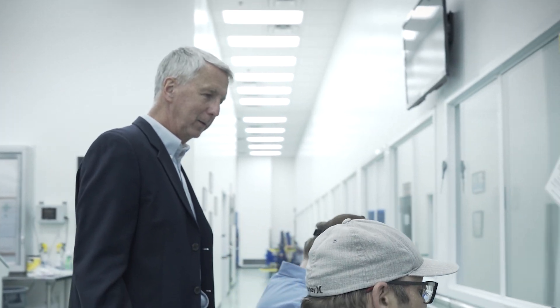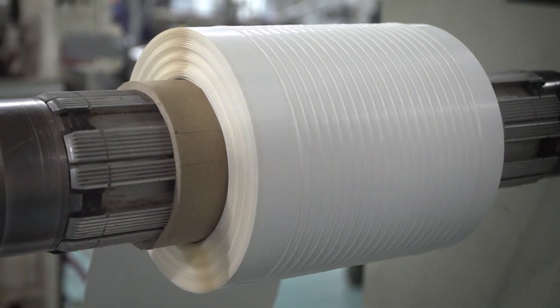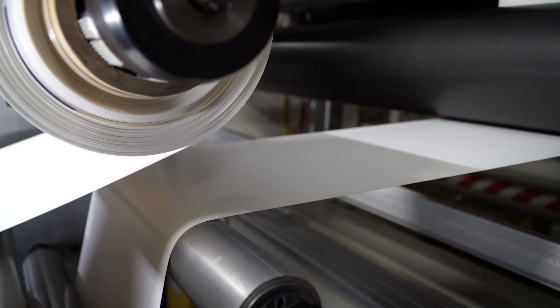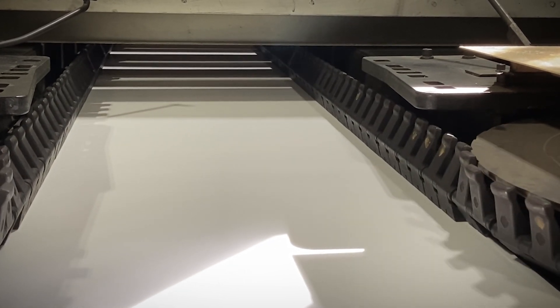I'm Rick Paquela, the Chief Technology Officer for ENTEK. We are excited to submit our solvent-free separator technology for this year's BCI Innovation Award. Innovation has always been an important part of ENTEK's core values. Our motivation for this project extends back to REACH in Europe and the long process we had to go through to continue our use of trichloroethylene at our UK plant. By extruding isotactic polypropylene, a nucleating agent, a surfactant, and a small amount of silica, we form a non-porous sheet. We then make sure the sheet contains the right beta-crystal content through the manufacturing process.